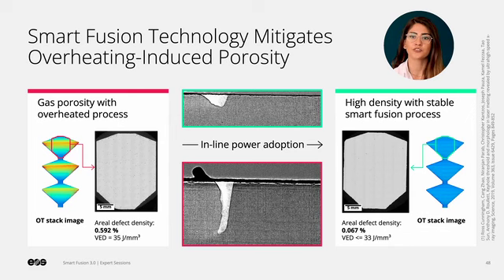Smart Fusion technology mitigates overheating-induced porosity like keyhole porosities. In this slide, we present an optical cross-sectional image of two heat demonstrator parts with the OT stack images captured during the manufacturing process. On the left side, we see a part that has been built using high volume energy density process parameters, while the right one was built with Smart Fusion and with the inline laser power adjustments.